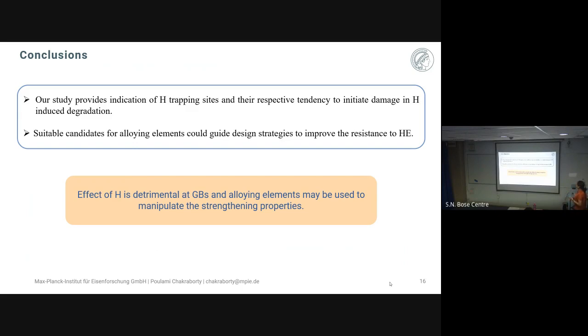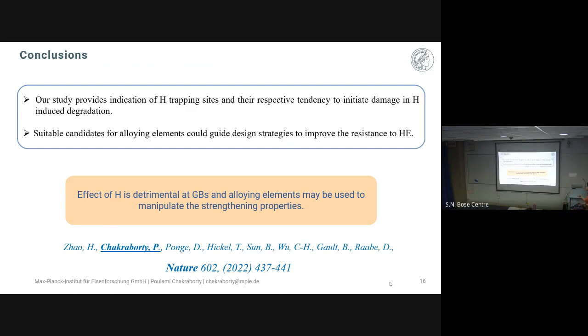And this is the first time it was successful that our aluminium alloy was electrochemically charged with hydrogen, and hydrogen has been measured in this particular work. And also we have been able to link up, not totally, but we have been able to provide some explanation from the DFT calculations. So this work can be summarized into this main message: hydrogen is detrimental if it goes to the grain boundaries, and alloying elements may be used to further manipulate the strengthening properties. This work has been published in a recent Nature paper with my colleague Zhao, who did all the experimental work, and I have done all the DFT calculations.